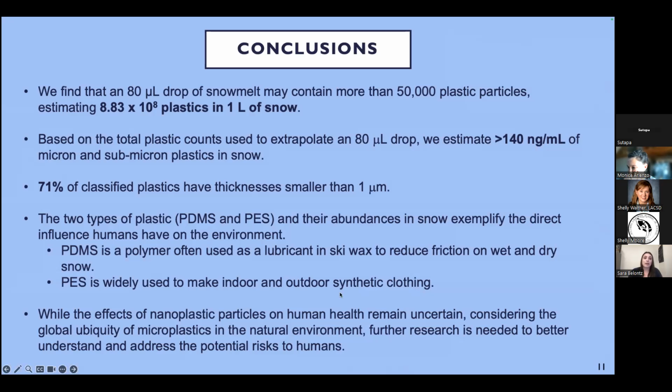And of these classified particles, 71% of them have thicknesses smaller than 1 micron. So very, very, very tiny. And when it comes to the compositions of the particles that were identified, it really does exemplify the direct influence of humans in the environment, especially when it comes to PDMS.